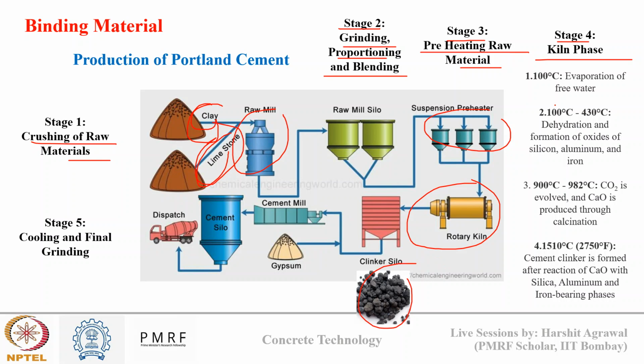So what is happening inside this kiln phase? You can see in this flow chart that in different temperature ranges inside the kiln, different activities happen with this proportioned raw meal. Initially at 100 degrees Celsius, evaporation of free water happens. Then from 100 to 430 degrees Celsius, dehydration and formation of oxides of silica, aluminium, and iron takes place. Then from 900 to 982 degrees Celsius, CaCO3 decomposes into CaO, releasing CO2. So we get CaO. Then at a higher temperature up to 1510 degrees Celsius, the cement clinker is formed, where CaO combines with silica, aluminium, and iron oxide to form different solid solution phases. The end product is known as cement clinker.